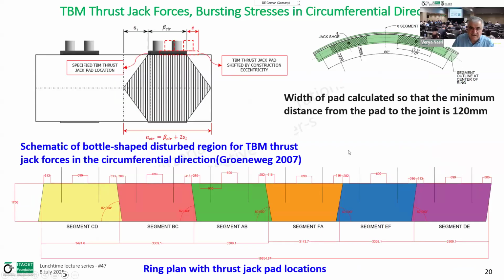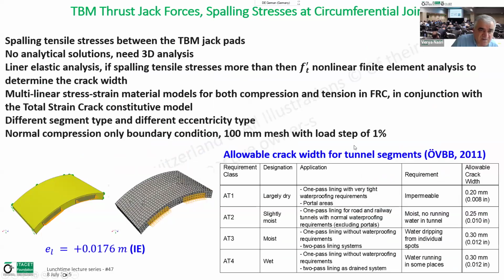And then we go to the spalling now. We don't have an analytical formula for spalling, so we have to do 3D analysis. We have to do a nonlinear analysis, and we have to verify the cracking. In this particular case, we use total strain crack constitutive model. There are different constitutive models for cracking based on a smeared model. Then we consider different segments and different eccentricities. And for boundary condition, we consider normal compression only boundaries. Here you see the allowable cracking from 0.2 to 0.3 from the Austrian Tunneling Association, depending on type of the application and level of dryness.